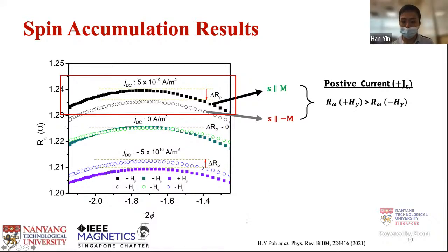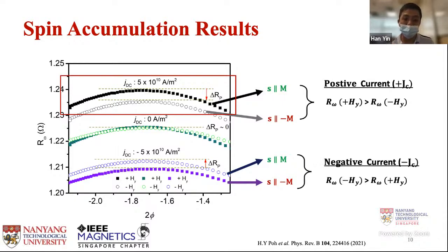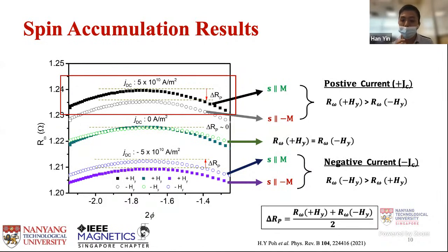Similarly, if you look at the bottom two graphs, we send the current in the minus X direction, so the spin will then be accumulated in the minus Y direction. And the amplitude when the field is in minus Y direction is higher as compared to positive HY. For JDC equals 0, we should see an identical amplitude, since the spin accumulation will be cancelled out when we add them together. So the change of planar Hall resistance, delta RP, can then be calculated by averaging the magnitude in R omega for plus HY and minus HY together.